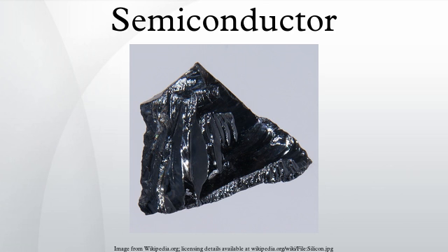In a metal, every atom donates at least one free electron for conduction, thus 1 cm³ of metal contains on the order of 10^22 free electrons, whereas a 1 cm³ sample of pure germanium at 20 degrees Celsius contains about 4.2 × 10^22 atoms, but only 2.5 × 10^13 free electrons and 2.5 × 10^13 holes. The addition of 0.001% of arsenic donates an extra 10^17 free electrons in the same volume, and the electrical conductivity is increased by a factor of 10,000.